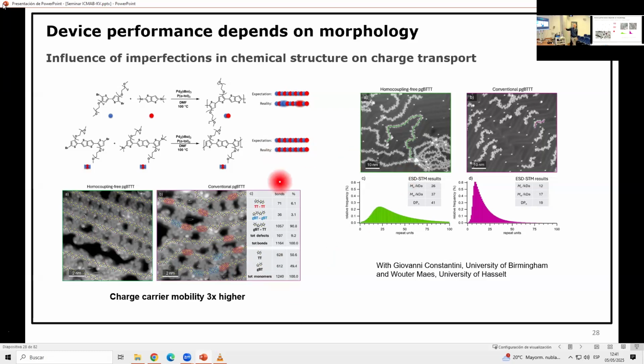And then we thought, oh, maybe we should not just do blue-red in monomers, but we should couple the blue-red monomer already, make it, and make sure that even if you miscouple, you would still have alternating. So then you can make a polymer which is definitely like the drawn chemical structure. So when we make this, indeed, with these STM techniques, you see that there's absolutely no miscoupling.